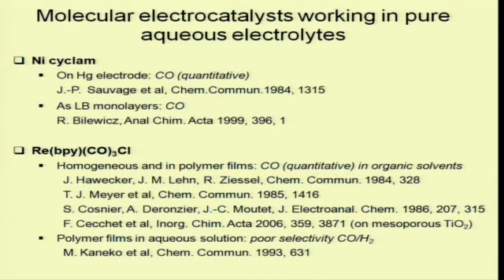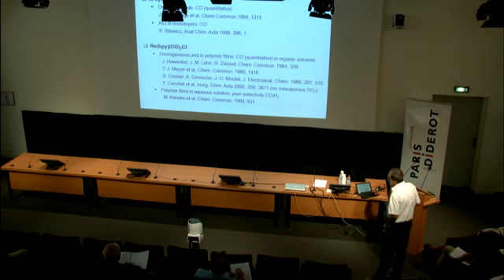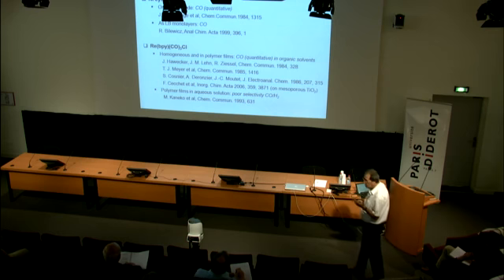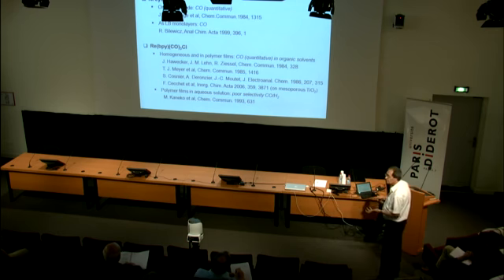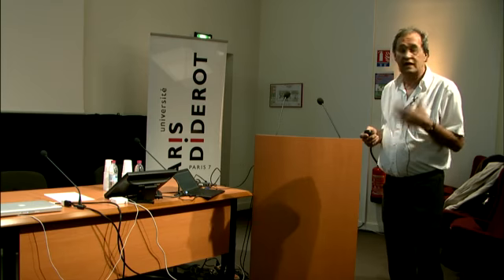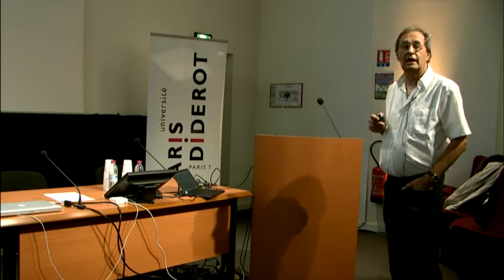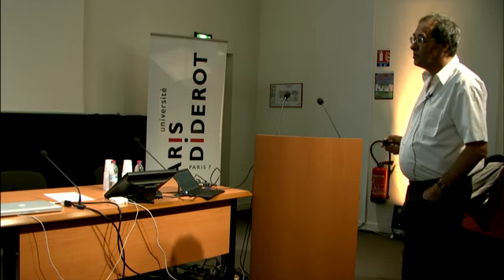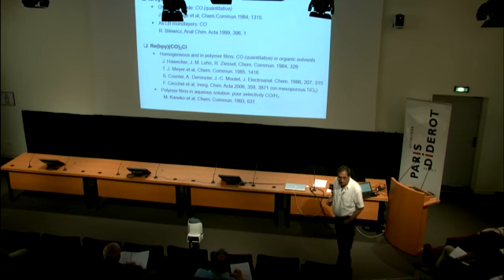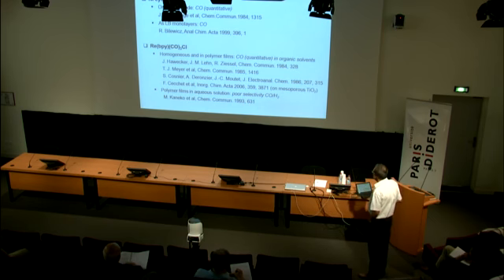Another important system is nickel cyclam by Jean-Pierre Sauvage and co-workers. The problem is it's necessary to use a mercury electrode because the complex adsorbs on the electrode surface, and also a monolayer, a Langmuir-Blodgett, because if you make a film, the film is not conductive enough. There is no possibility of electron exchange for this kind of nickel cyclam. And the last series was probably the most famous. It's a rhenium complex, bipyridine with 3 carbonyl and 1 chloro ligand.